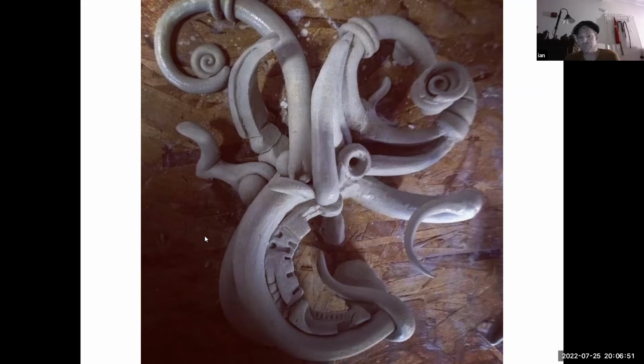Just lay down sand or lay down grog, and they'll act as kind of like ball bearings for when the piece shrinks, because those pieces are heavy, and they're going to do their shrinking thing. And if they don't have any sand or grog to lubricate that shrinking, they're going to crack right down the middle of the bottom.